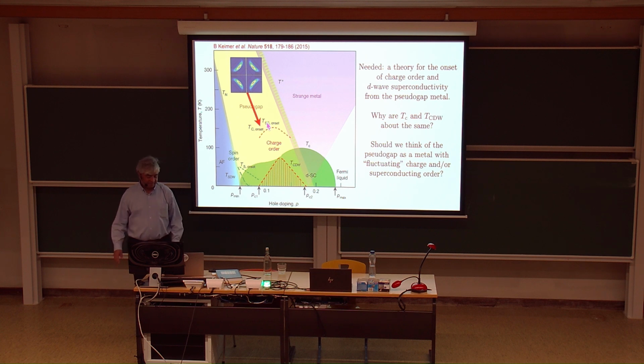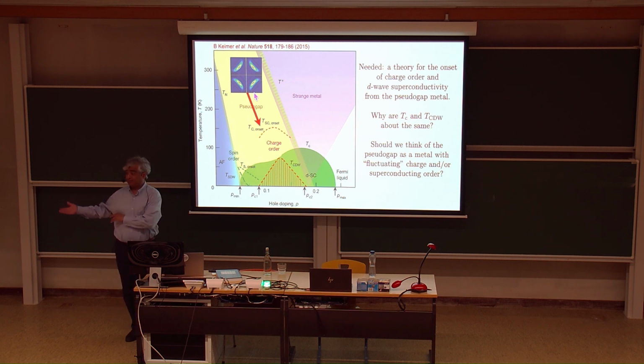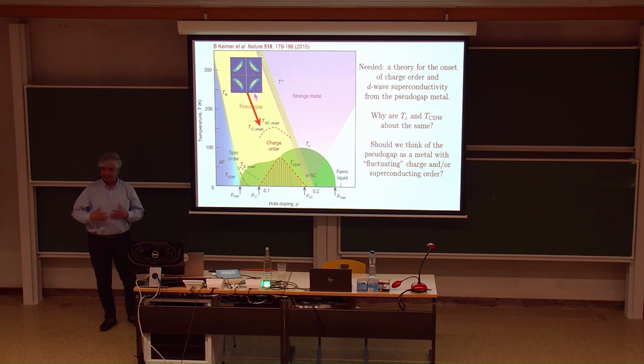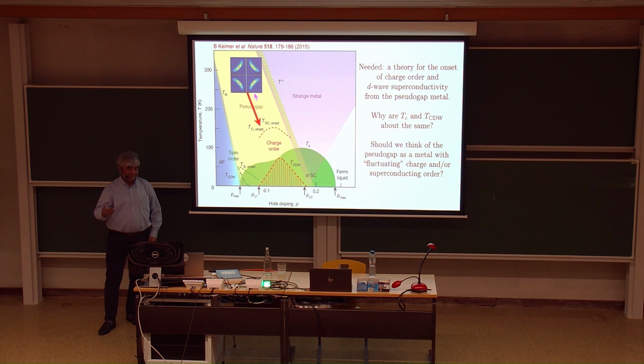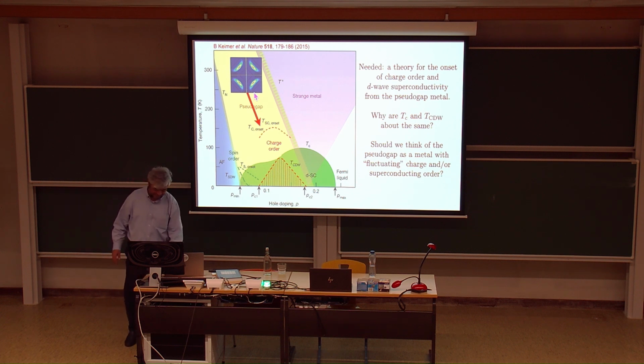But the basic point is that these temperatures, 200, 300 Kelvin, are still very low temperatures compared to the natural energy scale, which is almost 2000 Kelvin. And so the point of view is that the pseudogap, just like the Fermi liquid, is a quantum phase. It's not a fluctuating version of something else. It's a phase in its own right, which in principle could exist at zero temperature. Now, it doesn't exist in this material at zero temperature. Well, neither does the Fermi liquid. Almost any metal, if you go to low enough temperature, is a superconductor, or something happens. So these phases intrinsically have some very low temperature instabilities, or perhaps in this case not so low temperature. But they still should be thought of in their own right as their own quantum phases, not the fluctuating version of something else.